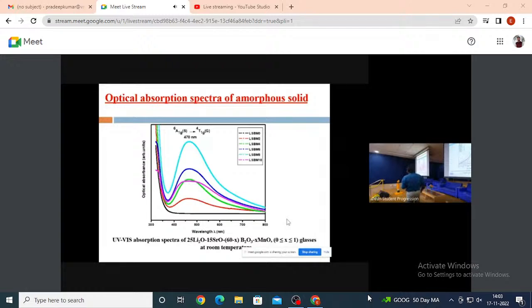And the second one is, in this absorption spectra, an enhanced absorption band. In this absorption spectra, an enhanced absorption band was found at 470 nanometers, which is due to the 6A1g to 4T1g transition of Mn2+ ions in the octahedral symmetry.